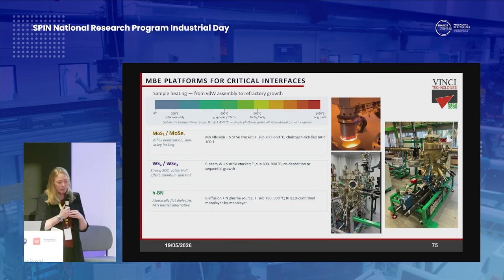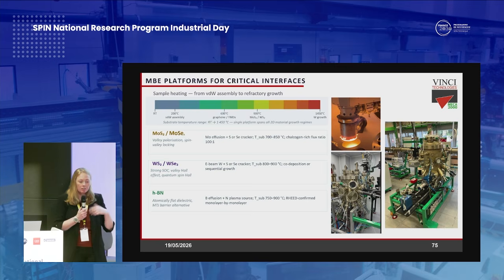And then in terms of the growth interfaces for these 2D materials, likewise, you see that the design of the equipment with regards to the sensors that you place in your system, we obviously simulate the fluxes from each of the effusion cells and from the E-beam, but despite that you have a certain amount of shadow effect on your detectors, on your sensors. That means that the positioning can become quite critical. With tungsten, for example, on the E-beam, placing the quartz sensor too close to the actual E-beam source means that you kill your quartz sensor immediately. However, rotating it on a rotatable flange can be a way to get around the problem.